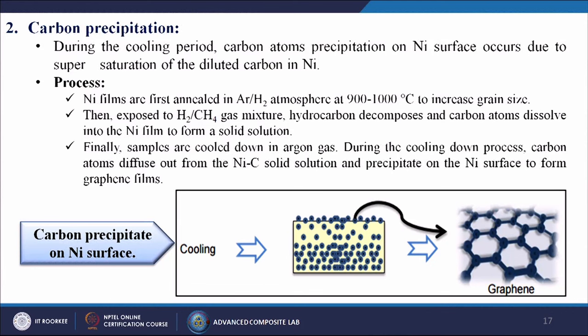Another process is known as the carbon precipitation process. During the cooling period, carbon atoms precipitate on the nickel surface due to supersaturation of the diluted carbon in the nickel metals. The nickel films are first annealed in an argon hydrogen atmosphere at 900 to 1000 degree centigrade to increase the grain size. Then they are exposed to a hydrogen and methane gas mixture, the hydrocarbon decomposes and carbon atoms dissolve into the nickel film to form a solid solution.